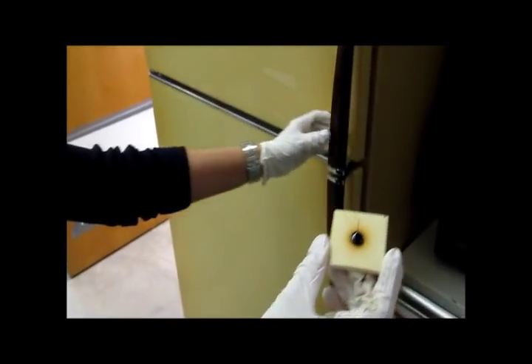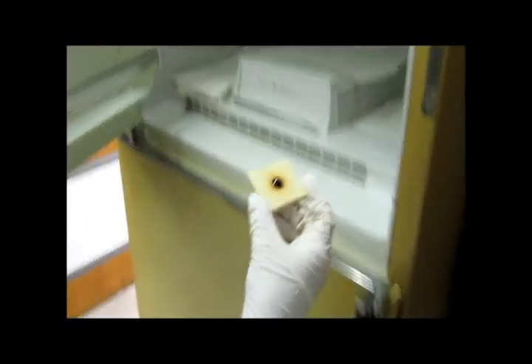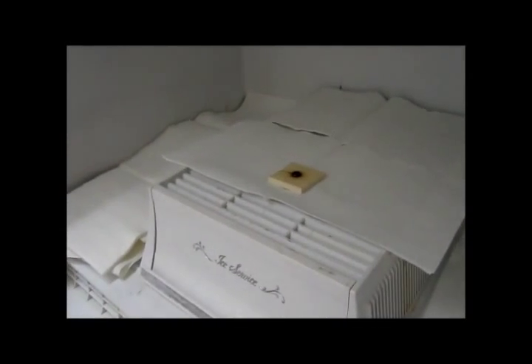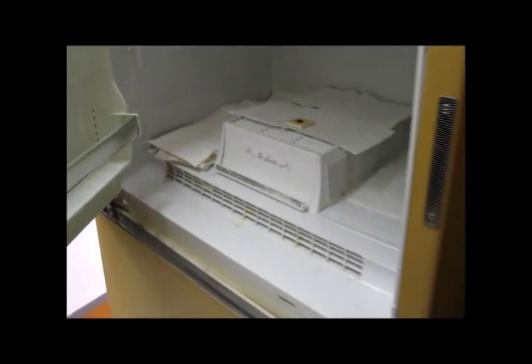To demold, cool the sample and mold for 15 minutes in laboratory conditions. If samples are not easily removed from the mold, refrigerate the samples for an additional one to two minutes before removing from the mold.